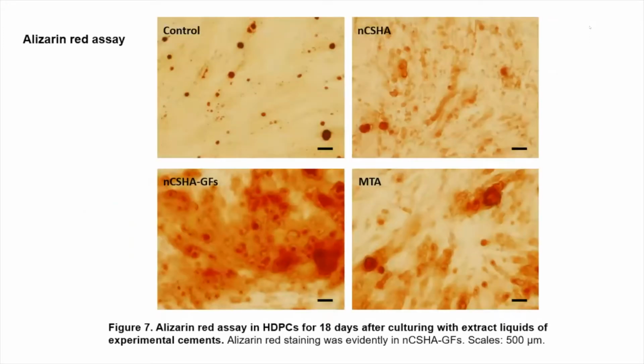And this slide showed the alizarin red staining in human dental pulp stem cells for 18 days after culturing with extract liquid of test materials. The staining demonstrated that the NCSHA showed widespread calcium deposition clusters, which is similar to the MTA group. And the NCSHA group containing growth factor showed much more red staining than the MTA group. That means the dental pulp stem cells have more calcification ability by the induction of the multi-growth factors contained in the group.